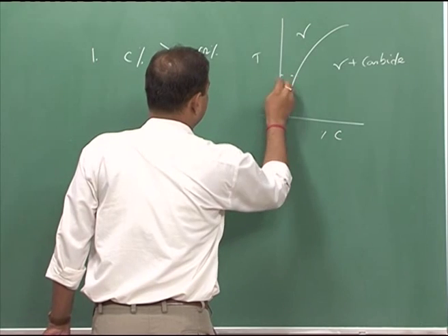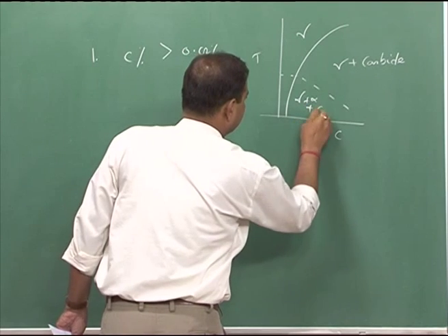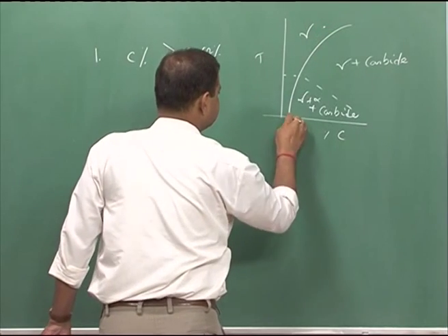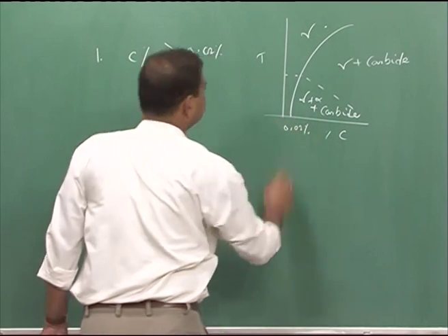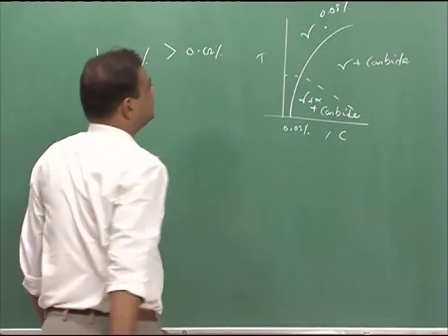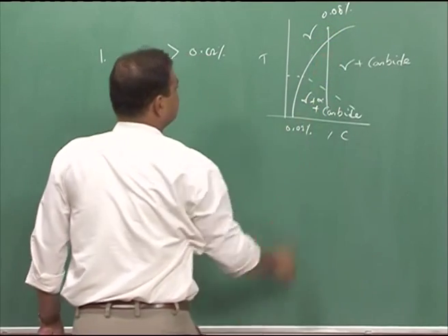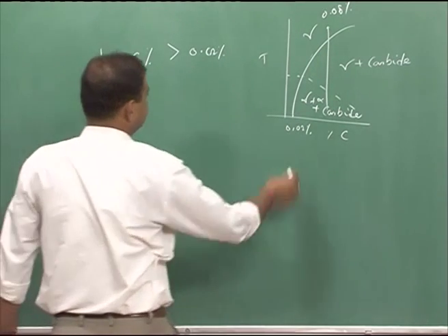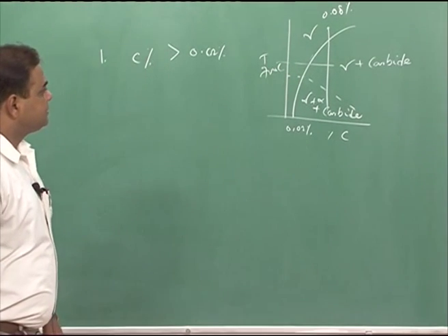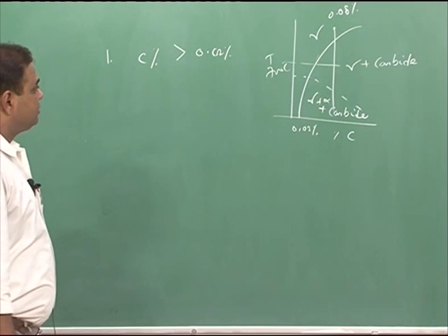Now, in between we have gamma plus alpha plus carbide. Now, this is around 0.02%, and if the carbon content is around 0.08%, and this is the solvus line, and if we cool it, and during cooling, let us say we are at this temperature around 700 degrees Celsius, at 700 degrees Celsius the chromium carbide precipitation is possible,